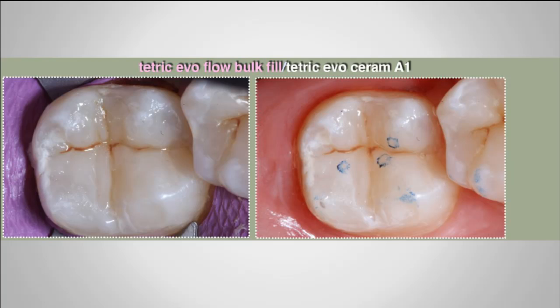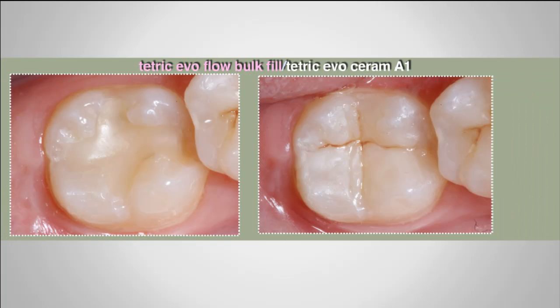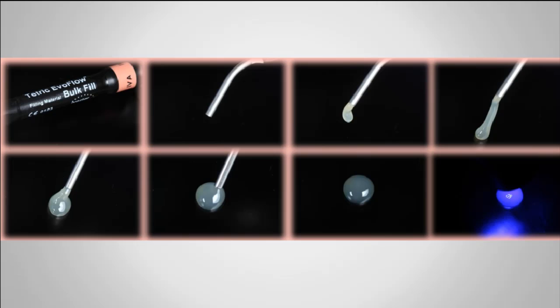The first layer is a bulk fill flowable one, and the last layer is going to be a regular composite with a very good result. Okay, so basically the advantage of this is you have a very fast restoration, you have less shrinkage on the interface, and also I told you that you have less bubbles inside.